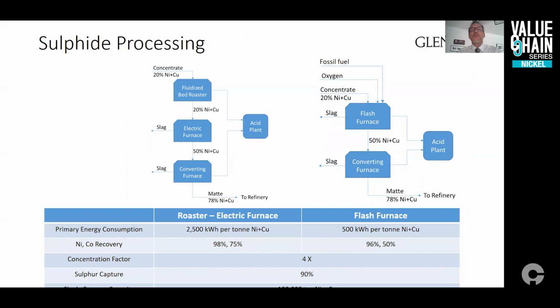In the electric furnace, the roaster product is melted using electrical energy. After melting, the gangue and iron oxide form a slag layer that floats on top of the remaining sulfide matte. The slag is skimmed from the furnace and sent to disposal. The sulfide matte, containing about 50% nickel plus copper, is processed in a converting furnace.